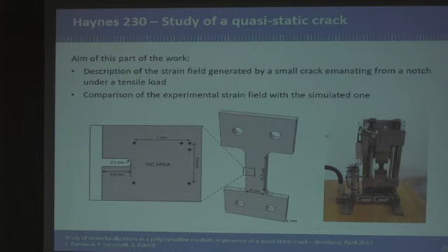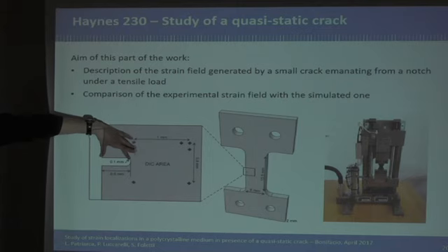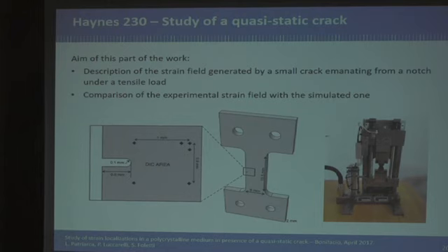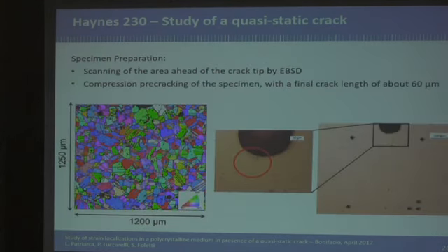Now, the idea is to use the crystal plasticity to model the crack tip strain field. So we machined this sample with this shape. This is a single edge notched sample with a depth of 0.5 millimeters. And now the problem is that we want to create a crack but without too much plasticity, because we don't want this pre-cracking to influence too much the quasi-static monotonic loading that we will do later. So in order to limit the plasticity, we decided to perform a compression pre-cracking procedure. We nucleated a crack in front of the notch by the compression pre-cracking technique, and